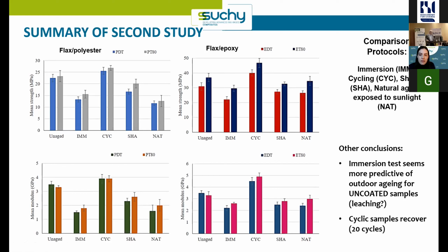And surprisingly, for the cyclic testing, after 20 cycles, we actually saw an improvement in properties compared to the unaged material. So that was, of course, a very nice extra thing we hadn't expected. So, as it concludes over here, immersion testing seems indeed quite predictive of outdoor behavior. But I have to say this is for uncoated materials.